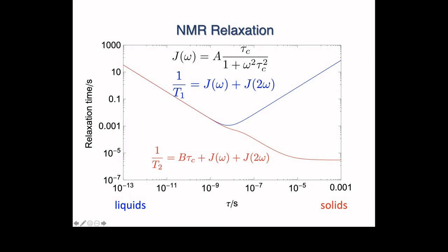In the liquid range, T1 and T2, for an ideal isotropic atomic liquid, they're exactly the same. So for water, for example, T1 and T2 are virtually the same number. But as you go into the solid phase, you can see they diverge and T1 becomes long again, T2 becomes short. Now, you don't have to remember all this, but just if you get the general idea that measuring the relaxation time tells us about mobility. And short relaxation times are solids and long relaxation times are liquids.